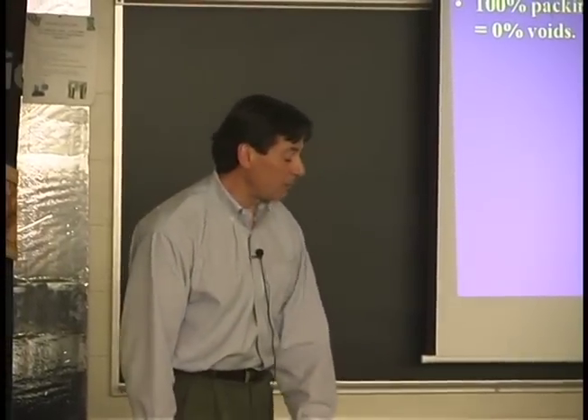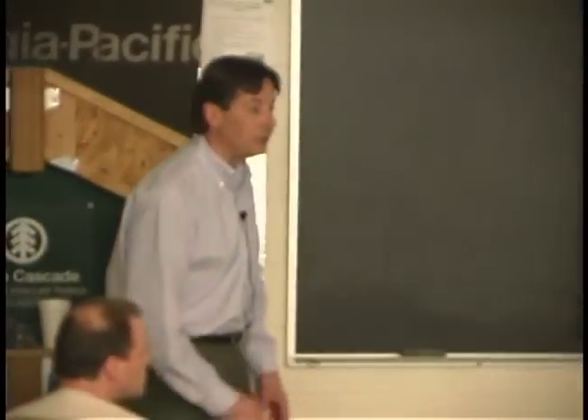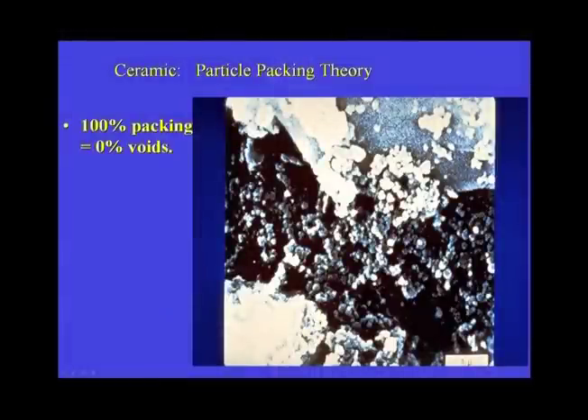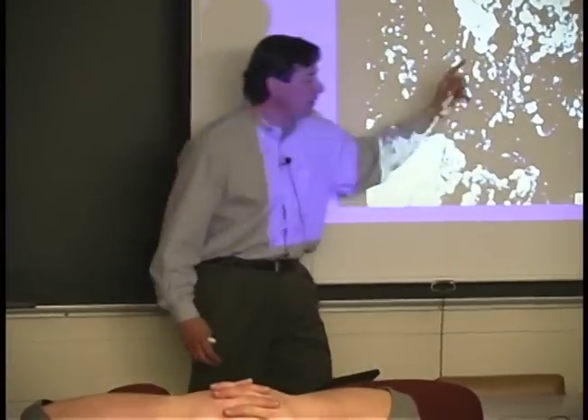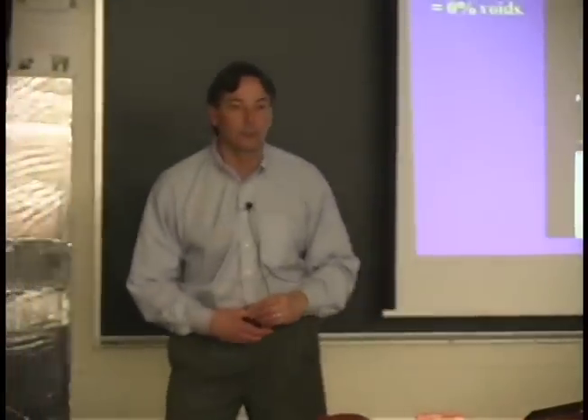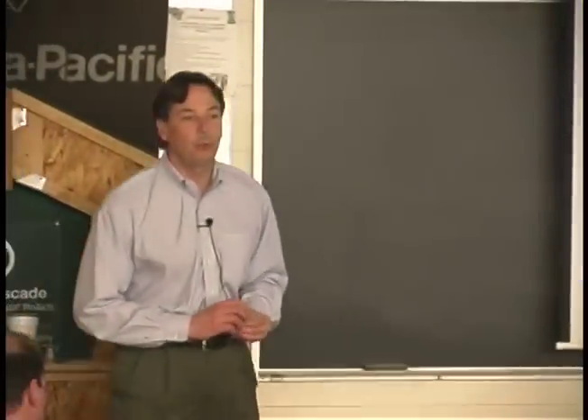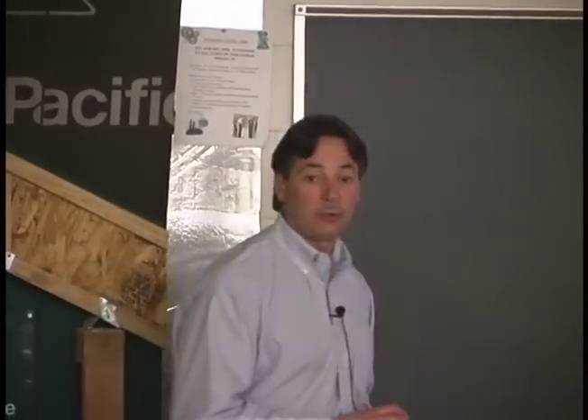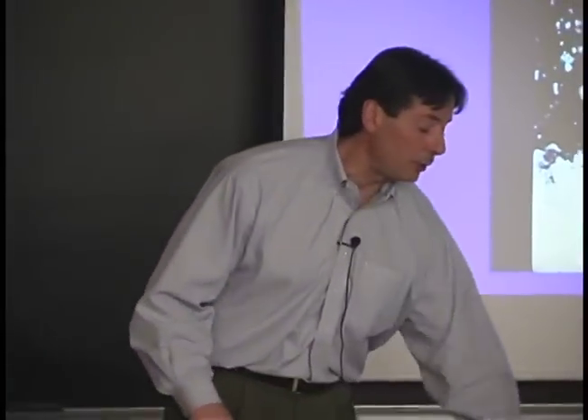This is another shot of trying to show the particle packing theory. Dr. Hover on the video was talking about fitting these little balls between other balls, and this is a shot of actually a cement grain. One cement grain here and one cement grain here, 1 micron scale, and that's silica fume particles mixed in within. I always use the example of filling up a barrel full of baseballs. You can only get those baseballs so close together, and you have void spaces between all the baseballs. Capillary pores in concrete, just like regular concrete.